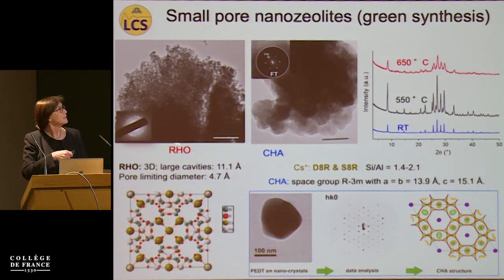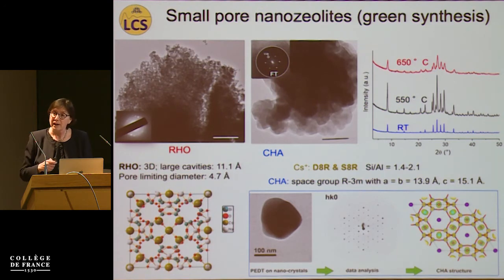RHO zeolite has very large cavities with a size of 11.1 angstrom, but at the same time it has a pore limiting diameter, and this pore limiting diameter could vary depending on the cation we put in the double 8 rings or single 8 rings. So this is a possibility to prepare highly selective materials which are able to separate molecules very similar in size, such as nitrogen and hydrogen, CO2, methane, etc.